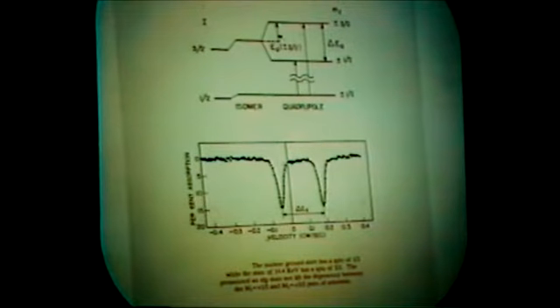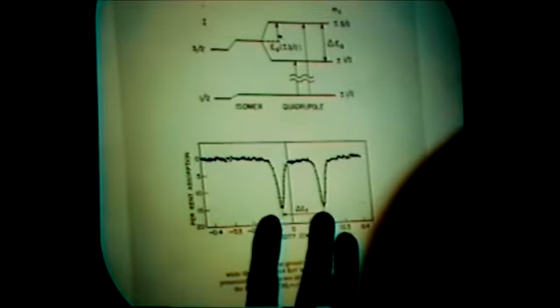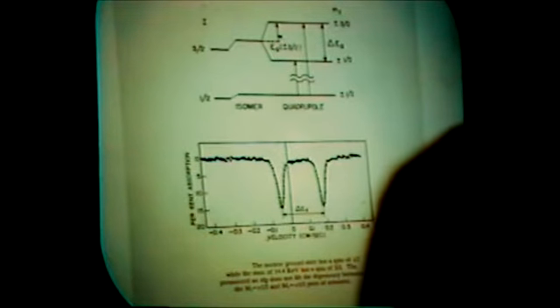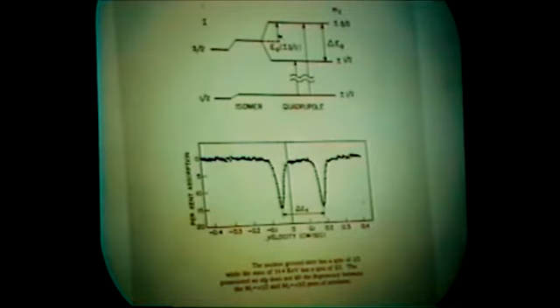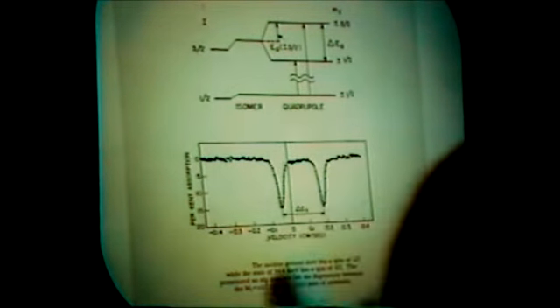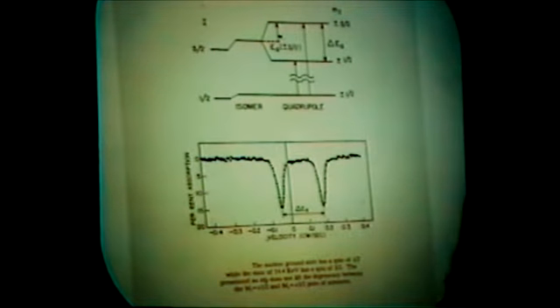So you find the position of these two lines at certain velocities, you subtract them, and that's the quadrupole splitting in millimeters per second. Now also you could notice that this spectrum is not centered around zero because there's an isomer shift. So you take the centroid, the middle distance between the two peaks, and you see how much it's shifted from zero velocity, and that's the isomer shift.